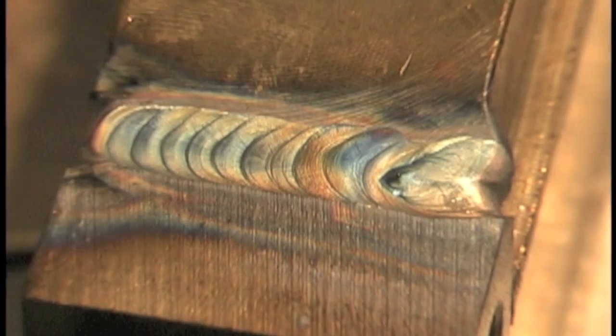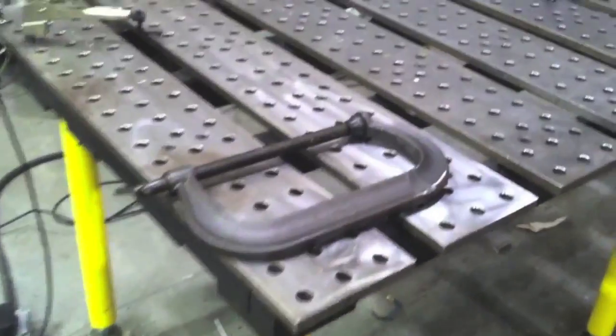You can try to match material sometimes and get the exact right rod to match the composition of the base metal, and then you can sometimes get porosity and all kinds of cracking going on because you didn't really guess the base metal correctly. Or you can just pick up some 309 and get it done, and everybody's happy. On this particular case, it was chamfered or beveled quite a bit, so I ran two passes to make sure it had adequate weld metal in there, unlike what you saw originally where it wasn't penetrated. And the parts were good - they're being used right now.